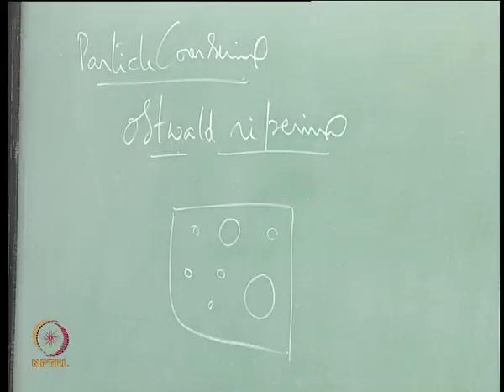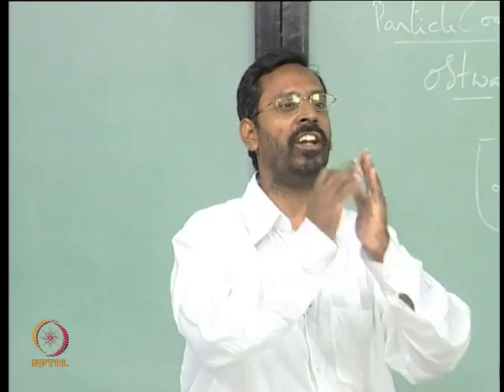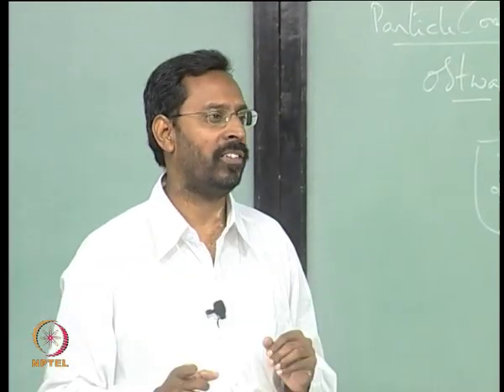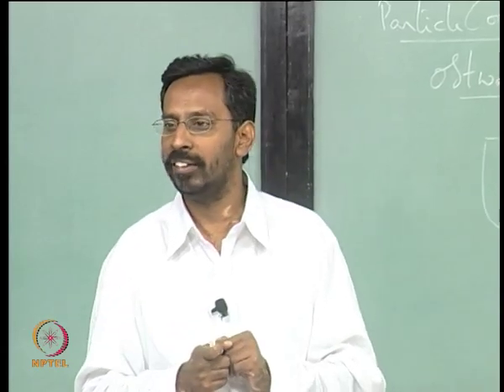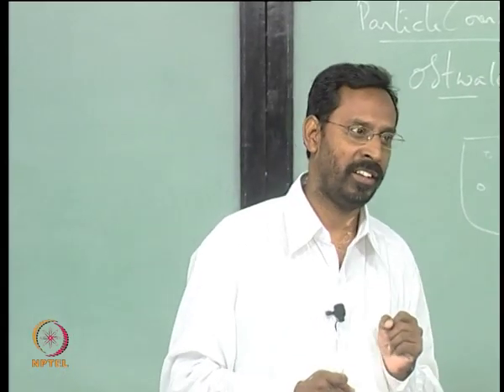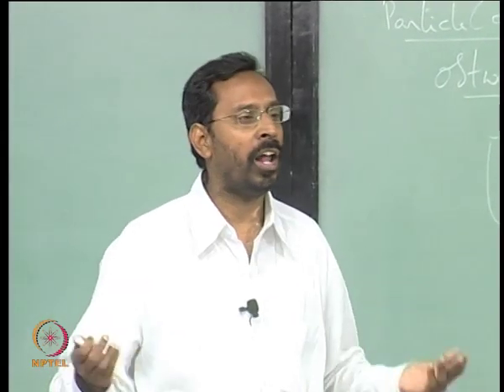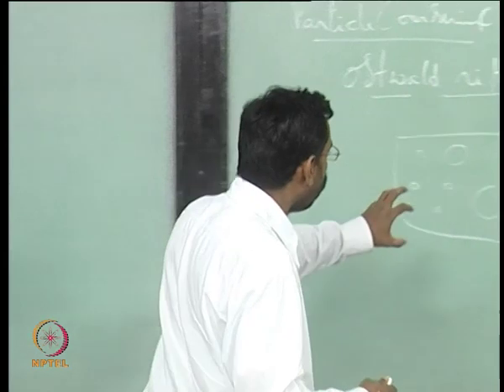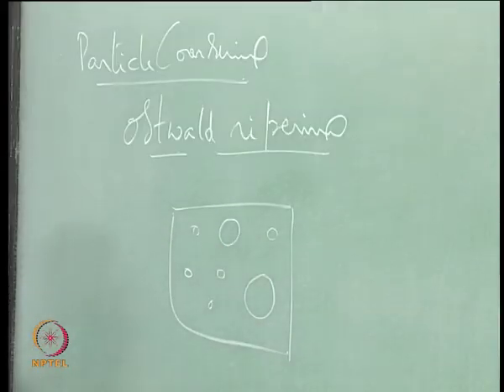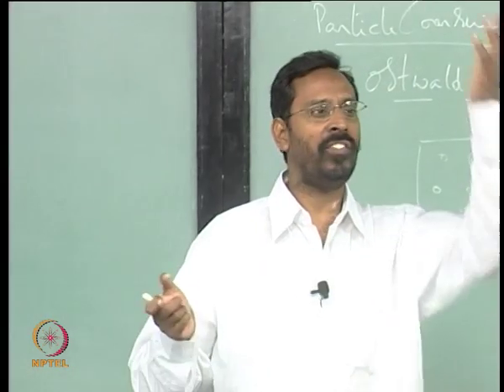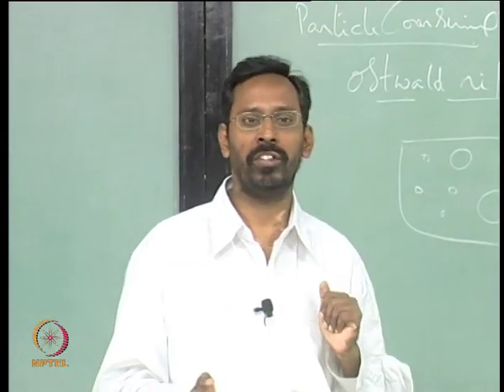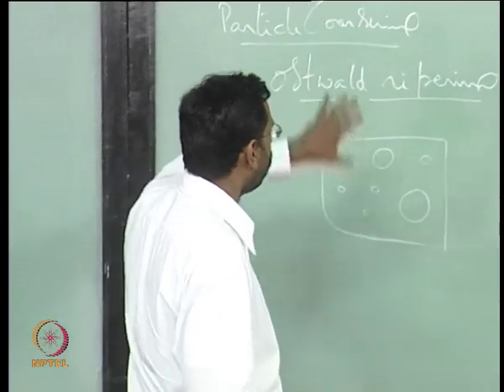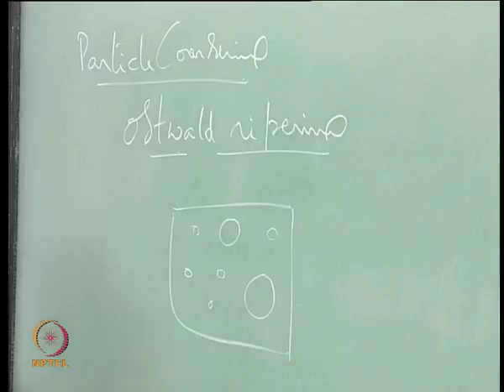Whenever you try to measure precipitate particle size, you will always see a distribution. There will be smaller particles, there will be bigger particles, and you can talk about the average particle size. That is why we always talk about average particle size, because we know pretty well that they are not all of the same size. Once you have this kind of distribution, and then you are heating this to a higher temperature. Let us say all this precipitation has taken place at some temperature, let us say during natural aging or artificial aging, and in service this material is now being exposed to a higher temperature. If it is exposed to a higher temperature, this kind of microstructure, how does it grow?